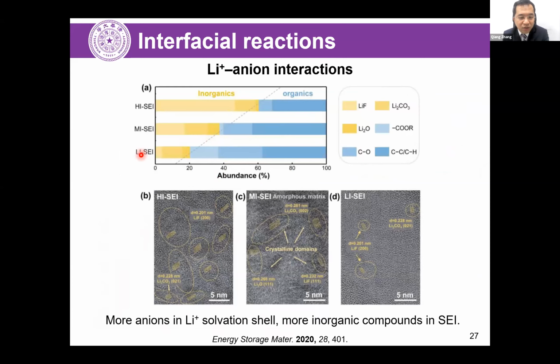So here is the low concentration electrolyte induced SEI. This one was the high concentration electrolyte induced SEI. And we found that with increasing salt concentration, the inorganic compounds increased significantly.